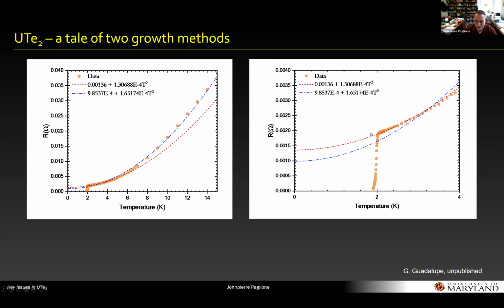And just to show you an example, if you fit in different ranges of T squared, you can get quite large factors in the zero resistivity. So Tc is perhaps a better measure, but even then you have to be careful about resistivity. We've seen lots of times that 2 Kelvin resistivity signatures of superconductivity do not necessarily correspond to the bulk signature measured in heat capacity. It could be a bit lower. So systematics matter.